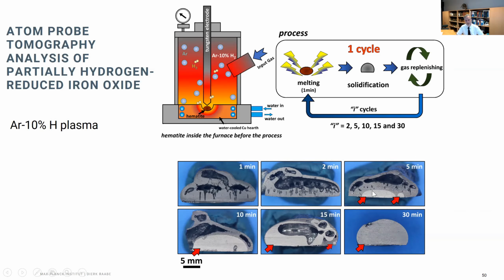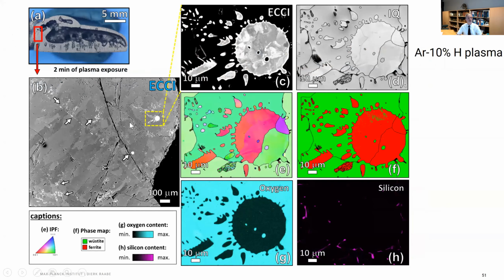And here you see some examples of the first experiments from Isnaldi Filho again, where you see how after several minutes of exposure of the material to this type of mixed plasma, you get pure iron. And this is just a fly-through, as you see here, of the complex array. This is just after 2 minutes of plasma exposure with only 10% hydrogen. You can, of course, try all different kinds of plasmas, obviously. And you see these beautiful structures that remind us a little bit of some art from Miro, for instance. You see here this big particle of iron, which has been formed splashy-wise amongst this wüstite. And that was just stopped in between after 2 minutes. And then when you go on with that, you get pure iron.